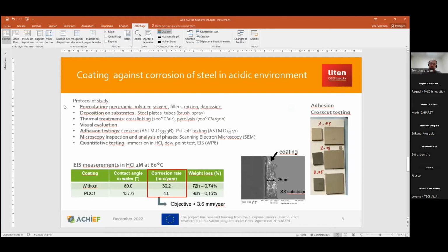For the second use case, the same procedure is performed, but in this case a different formulation is developed to act as a chemical barrier against acidic gas carried inside the tube. Quantitative testing like electrochemical impedance spectroscopy is used. Here in the table, you can see results of the performance of a coating reaching a low corrosion rate of about 4 millimeter per year.